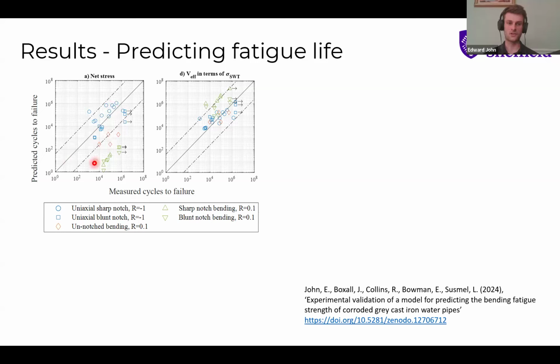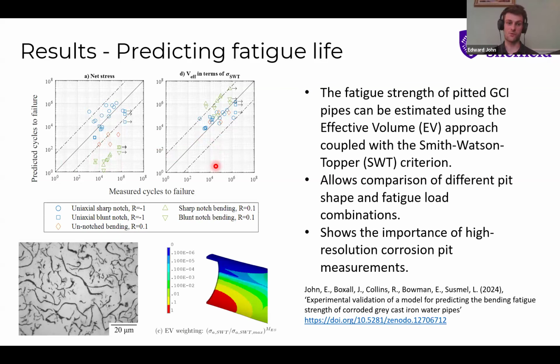So the left-hand plot shows the net stress. So that's basically the standard prediction you might do where you're just assuming uniform wall loss to the depth of the pit. So even where you've got a localized pit, you just look at how much wall is remaining and assume that that's the same all around the pipe. And then on the right, we've got a model here that's using a combination of two models. Actually, it uses the Smith-Watson-Topper criterion to account for the effect of the complicated, multi-axial stresses, and then also the effective volume criterion to account for the effect of localized pits. Basically, this provided pretty good predictions. So we're onto something here of being able to predict this behavior and predict which kind of pits are the most damaging.